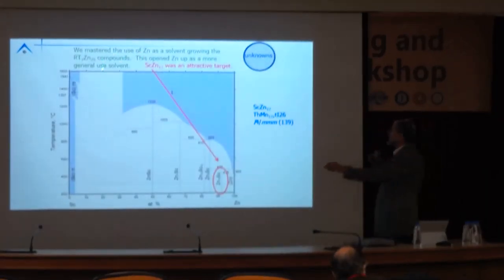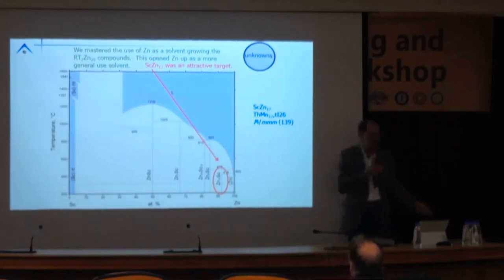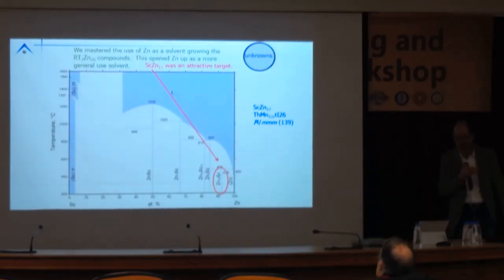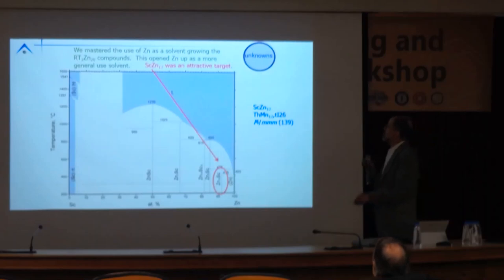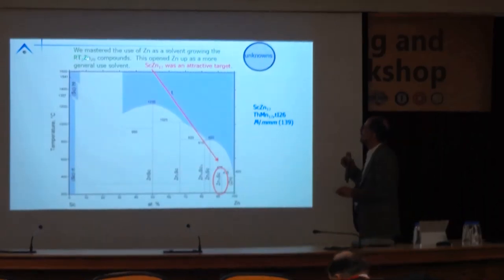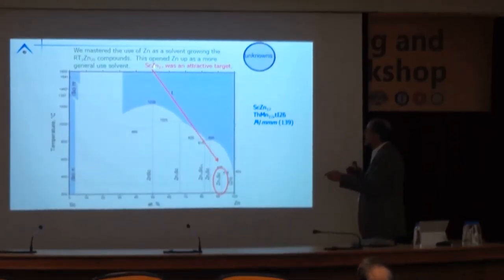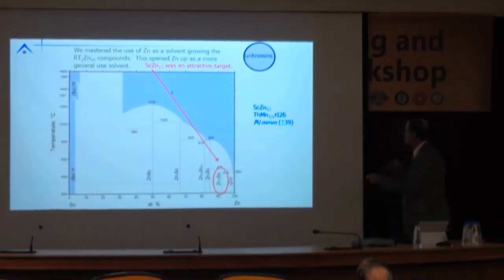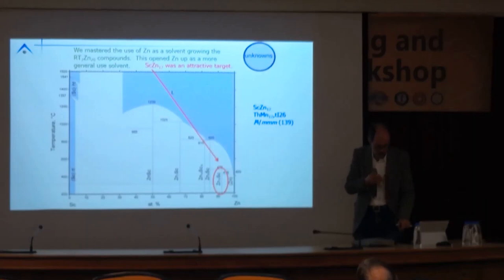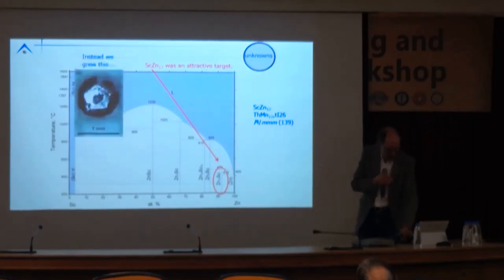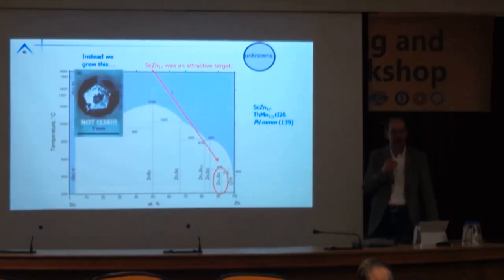We figured out how to handle zinc as a solvent when we were looking at rare earth transition metal zinc 20 materials. I will talk about those materials in this discussion. On the other hand, having mastered zinc, I had two undergraduates one summer, and I figured, let's look at scandium zinc 12. It might be an interesting material with dilute scandium. Okay? This is a tetragonal material whose structure is known. Okay? We grew this. Without any measurements, the one thing I can say is that's not tetragonal.